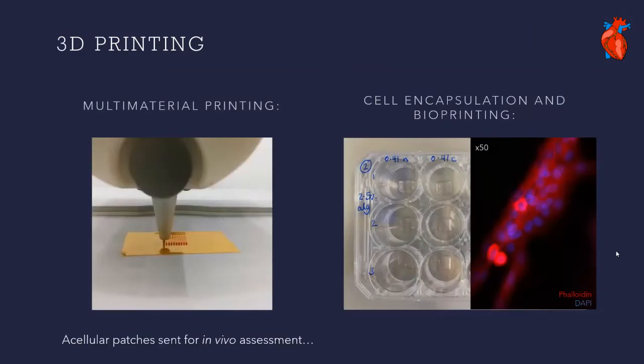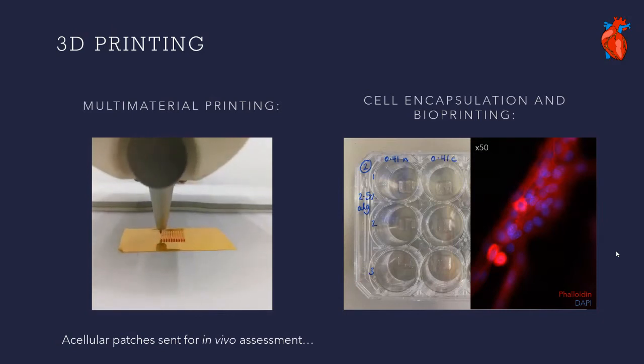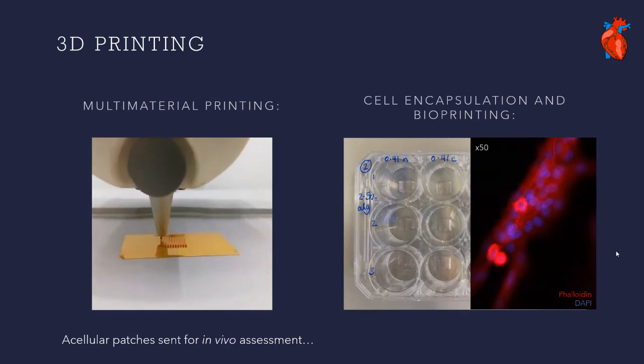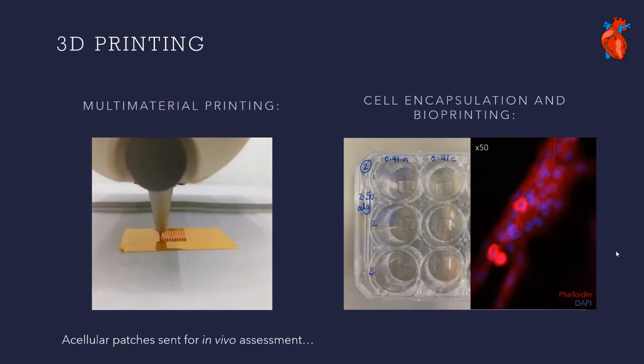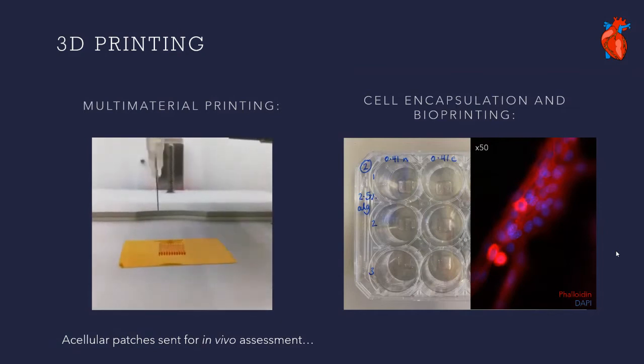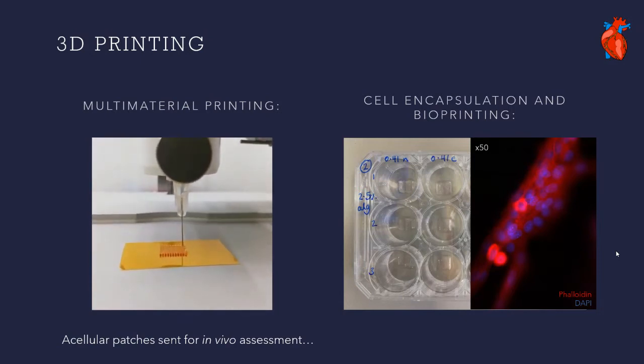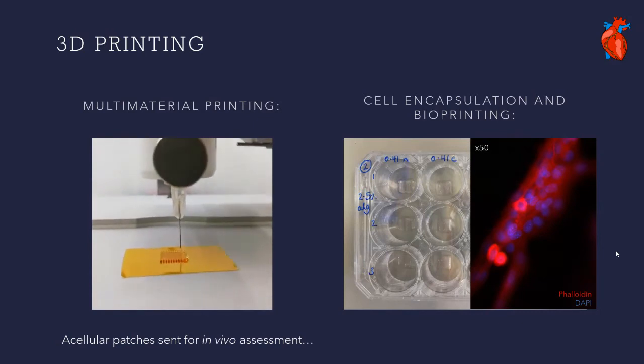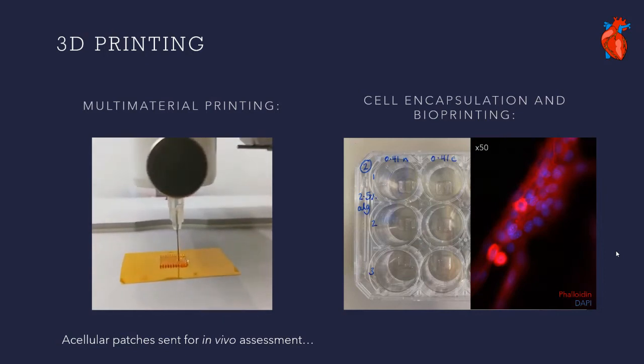And so all of this comes together for our processing technique, which is 3D printing. As I said, I'm using PHAs and alginates, and we multi-material print these in alternating struts of each, PHA and alginate, with struts going in one direction and then in a perpendicular direction to produce our patch. We've so far produced some acellular patches, which have been sent to a collaborator for some in vivo assessment to check their suturability onto a mouse heart and also to check for biocompatibility in vivo. And we're moving on this. Next up, our research is moving towards bioprinting, so encapsulating cells within the alginate.